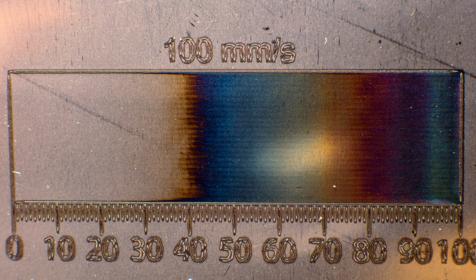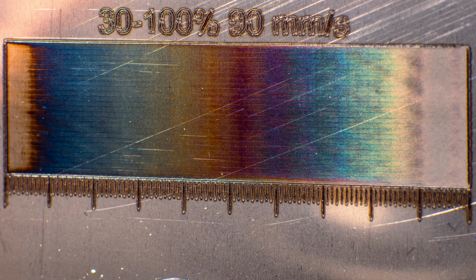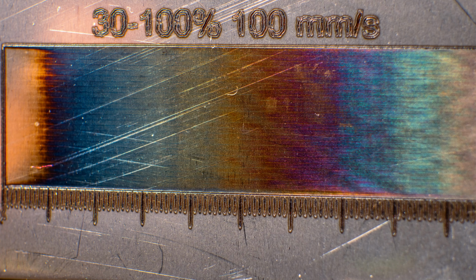These are going to be really useful for narrowing down on a certain range of colours that I want to put in any of my images. You can also see from the close-up macro photos that the 0.05mm line spacing hasn't left any gaps in the different lines, leads to much more vivid colours and none of that horizontal banding.